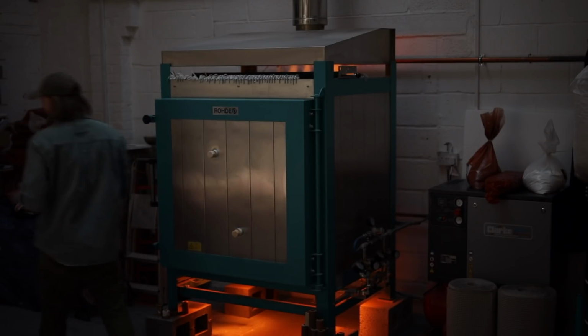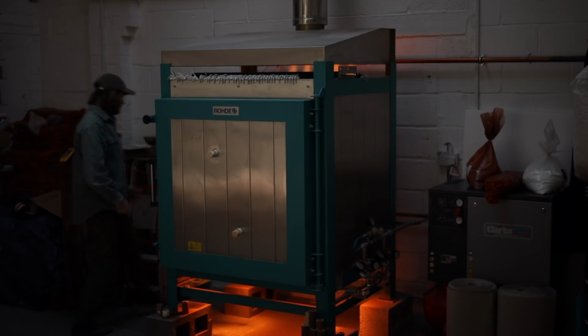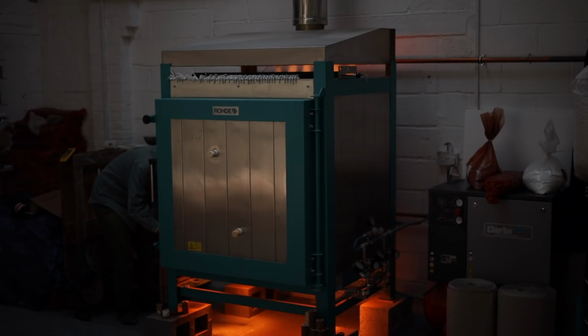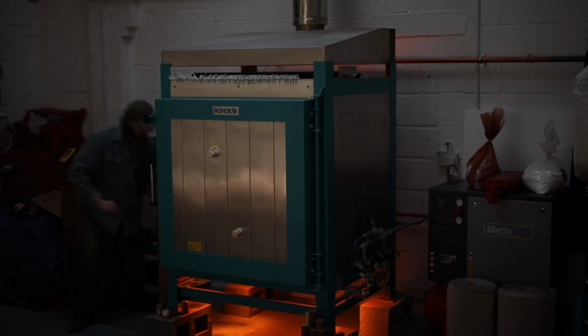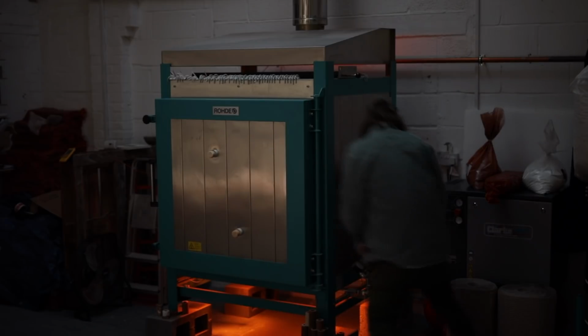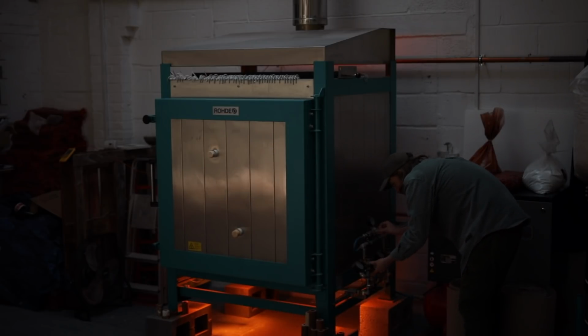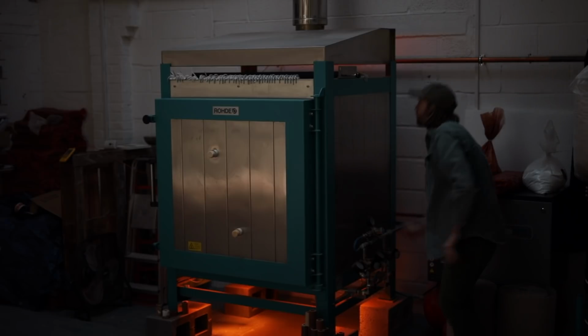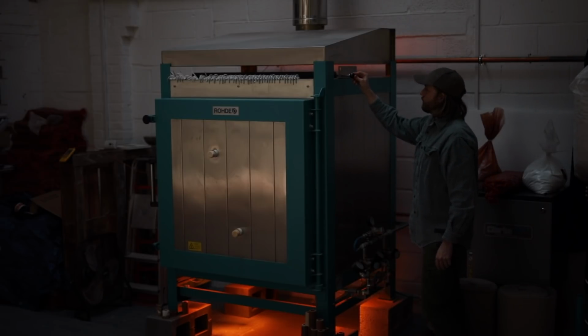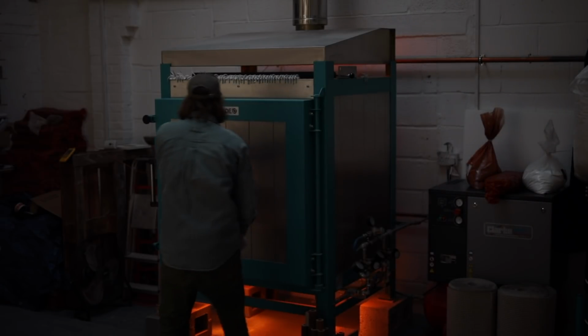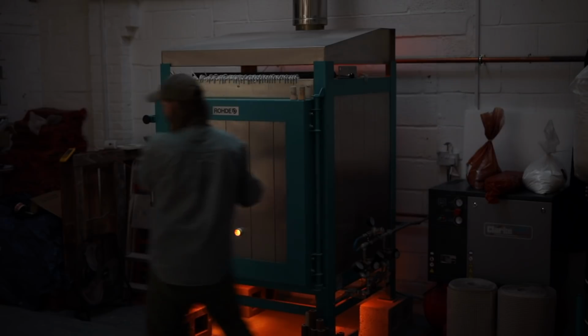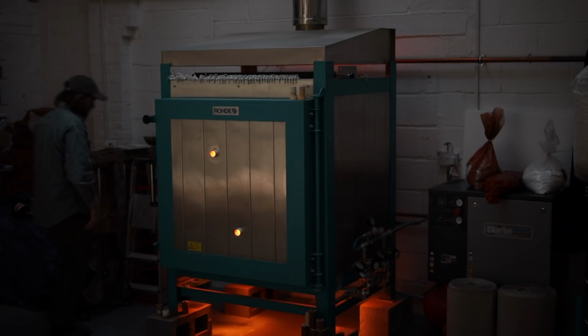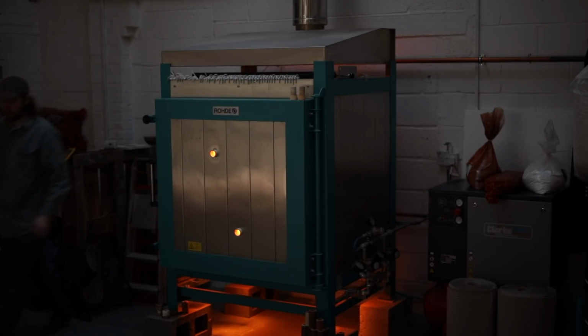Once the pyrometric cones have bent over sufficiently, it's time to end the firing. I always start by switching off the mains valve, and then each individual burner, and I always welcome the sound of silence that comes after firing for 9 hours straight. There is one last thing I do, which is open the dampers and the spy holes to quickly let the kiln cool from 1290 degrees to 1000 degrees Celsius, a process called crash cooling, which supposedly helps retain colour and gloss.